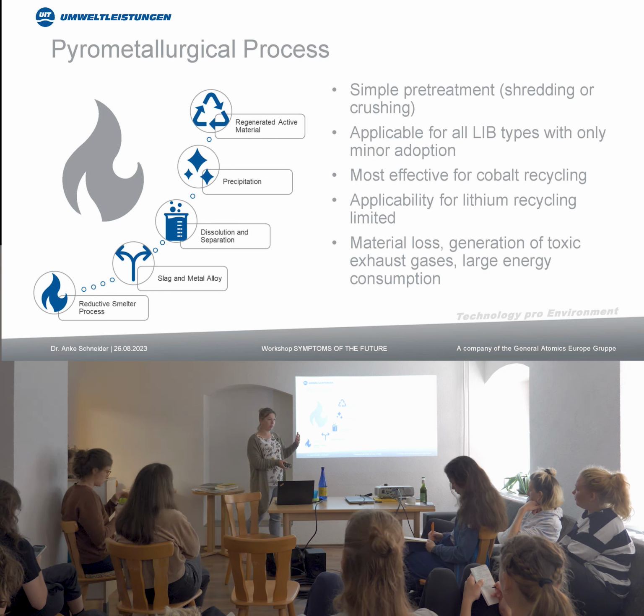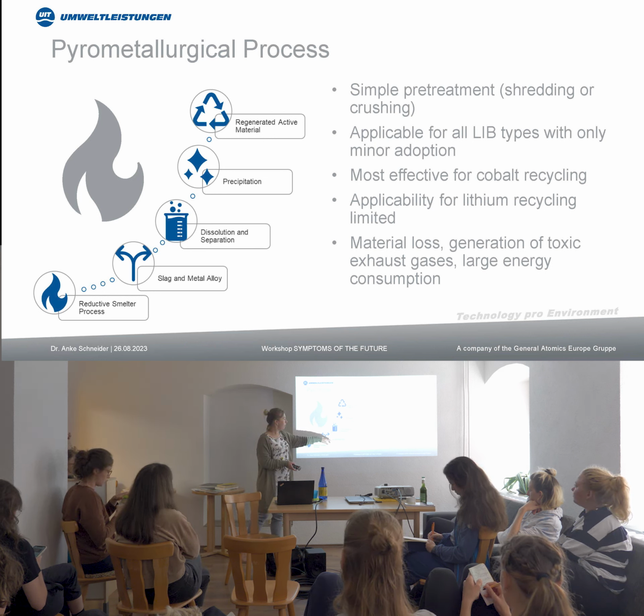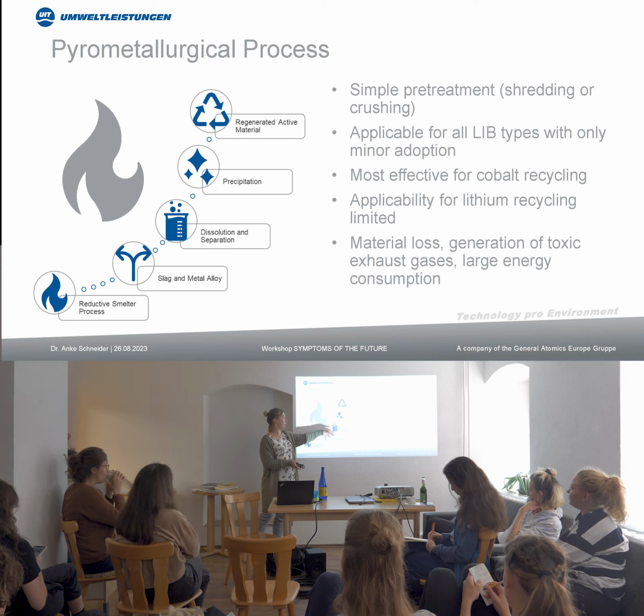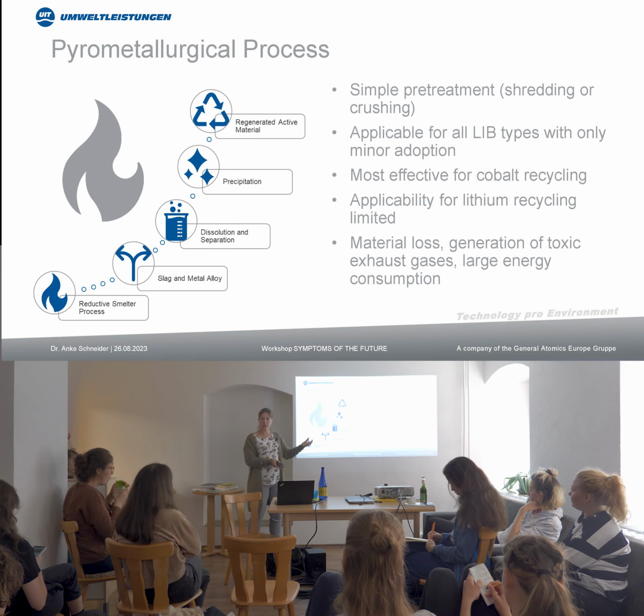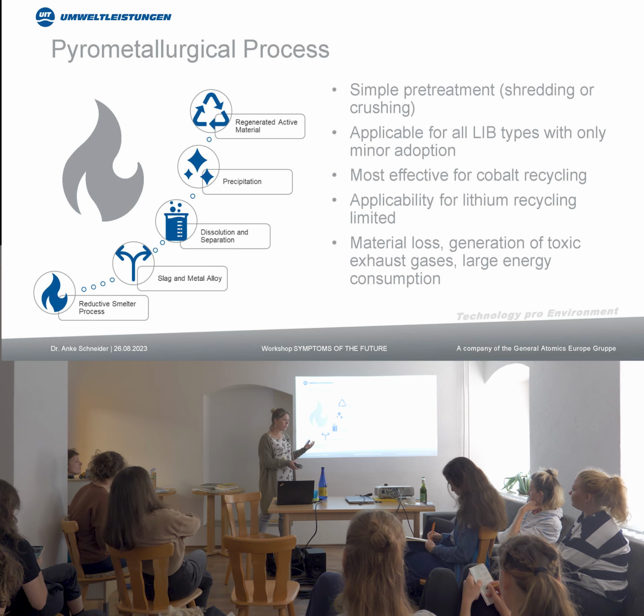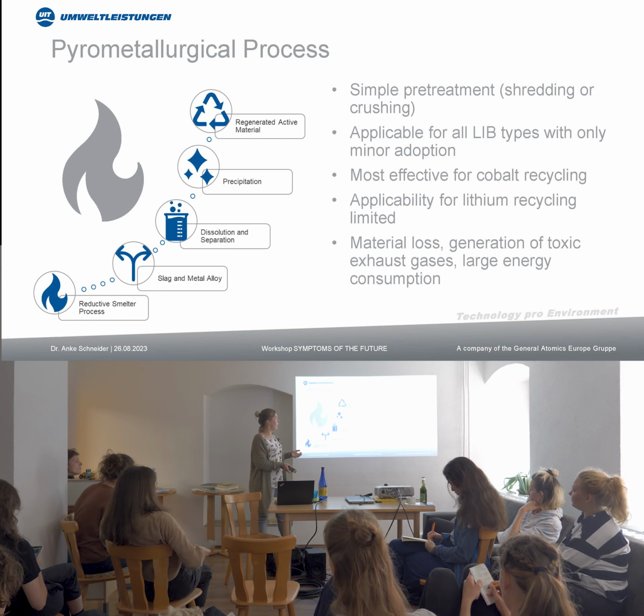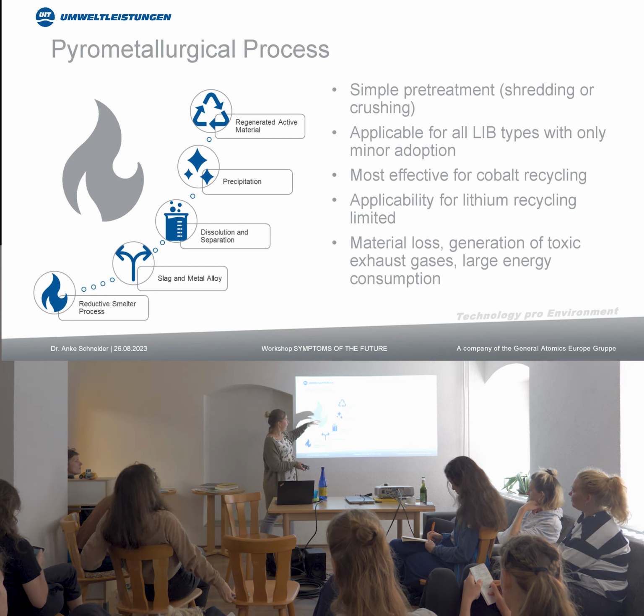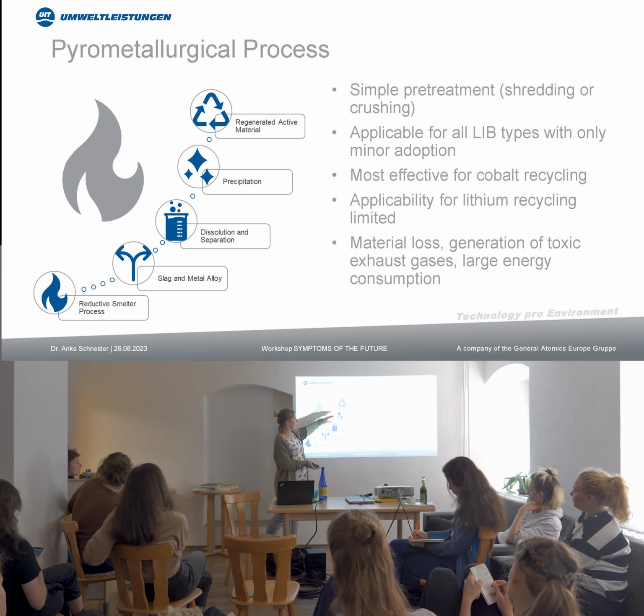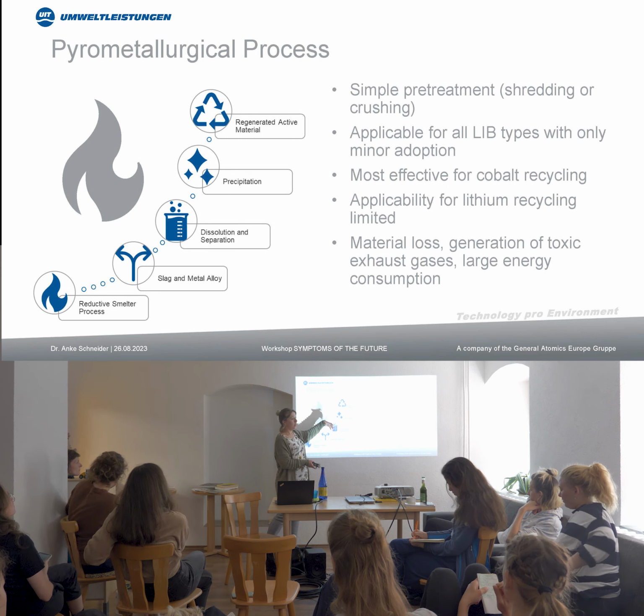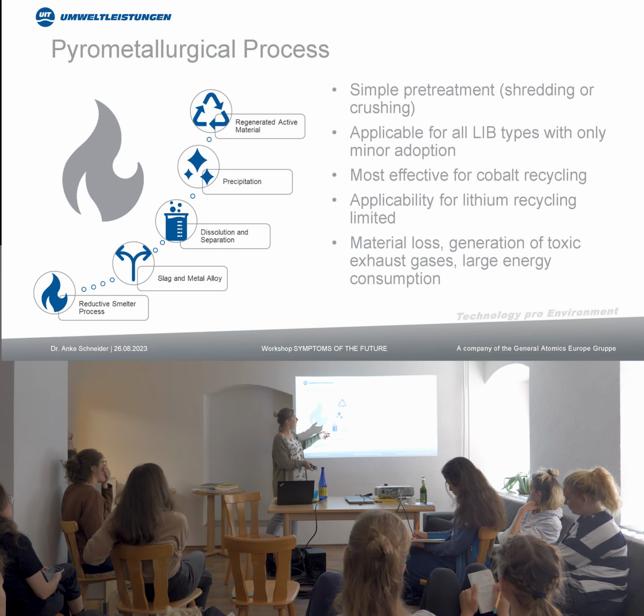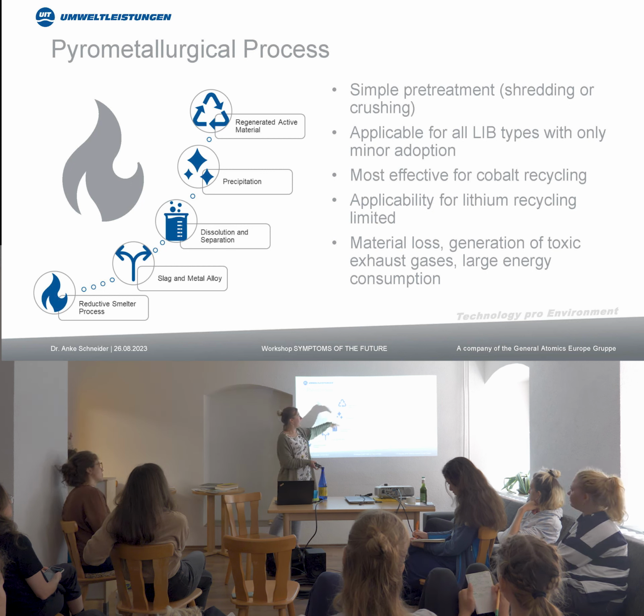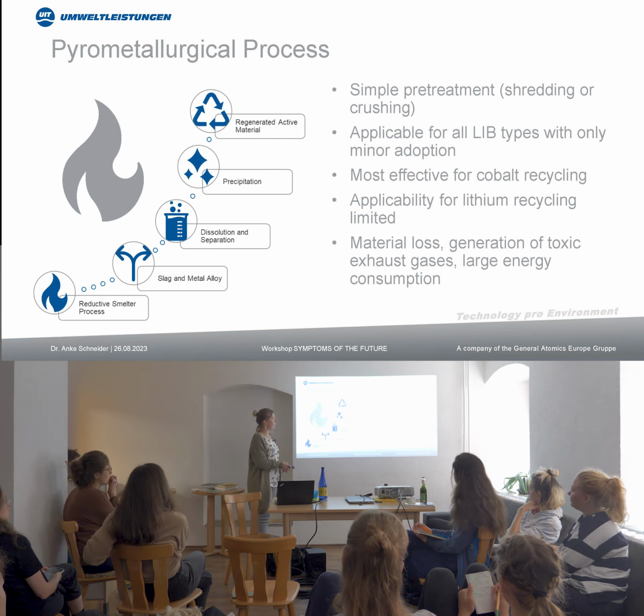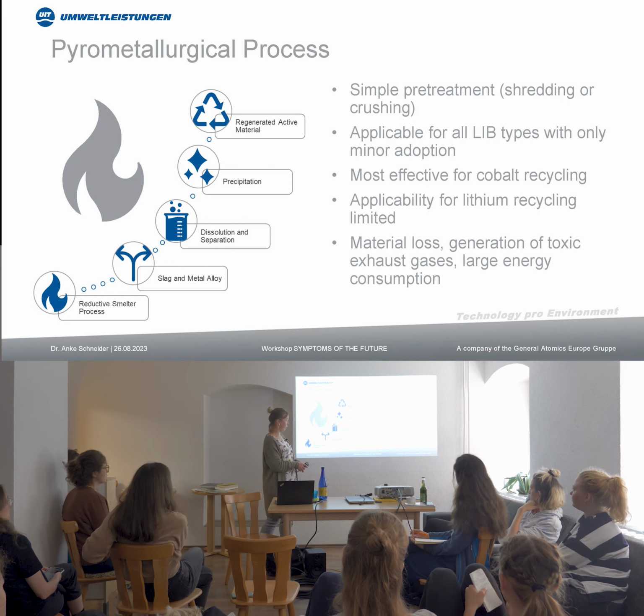And then you have a slag, which is mainly composed of lithium and aluminum. And if you look at the lithium side, then we need to leach this slag or dissolve the lithium out of this slag, which is done by acids. And then afterwards we have the lithium in solution, can precipitate this to lithium carbonate or lithium hydroxide and produce the regenerated active material.